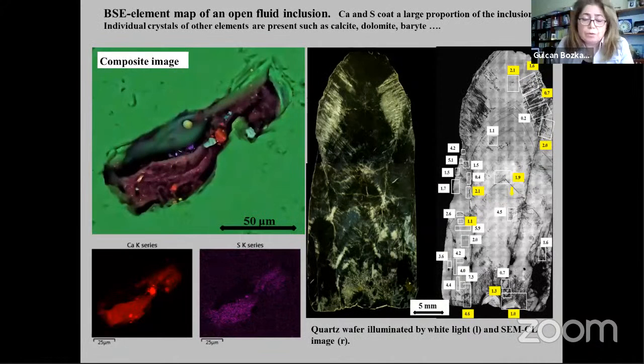The image on the right shows a cross section of euhedral quartz as a double polished fluid inclusion wafer. The left one is illuminated by white light from above, with areas of dense accumulation of fluid inclusions appearing as white linear features. The right one is the SEM cathodoluminescence montage showing growth zones and different fluid pulses during precipitation. Here the fluid inclusions can be seen as black linear features.